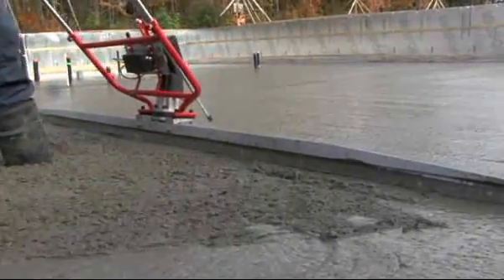The Magic Screed and the EZ Screed require the same conventional method as hand screeding. Place the concrete. Depending on the size of blades used, prepare four leveling points at the needed distance. Screed approximately 12 to 16 inches wide on both sides following the leveling points, creating an unscreeded surface between the wet pads. Then, with a raker following behind you, making sure that you have the necessary amount of concrete on the back of the blade to create a rolling effect, screed the concrete, keeping the blade as flat as possible while using the cutting edge.